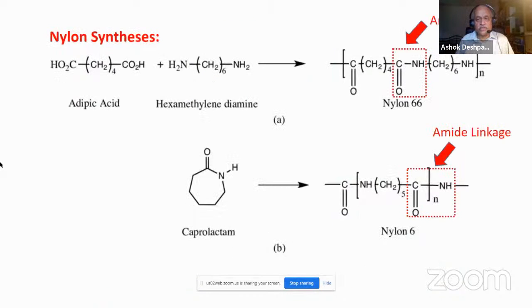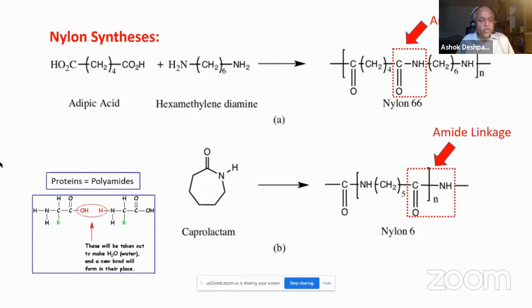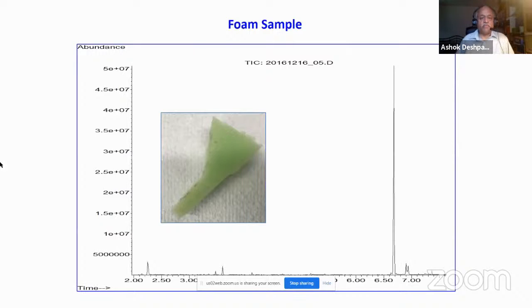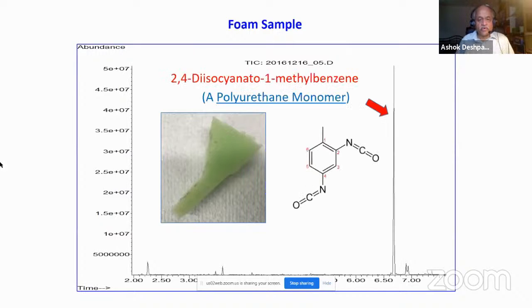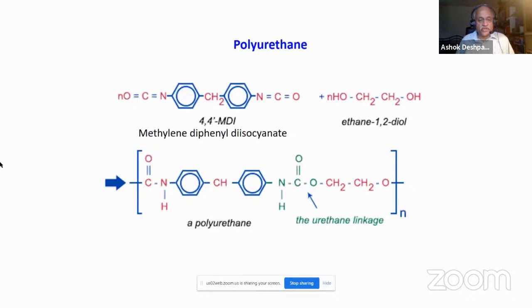Nylons are polyamides. The nylon 6,6 is prepared from polymerization of adipic acid and hexamethylene diamine, while nylon 6 is prepared by polymerization of caprolactam. Proteins are also polyamides. They are formed by the polymerization of different amino acids. This foam sample has a marker compound for polyurethane. Polyurethanes are formed by the polymerization of methylene diphenyl diisocyanate and ethylene glycol. They contain a unique urethane linkage.